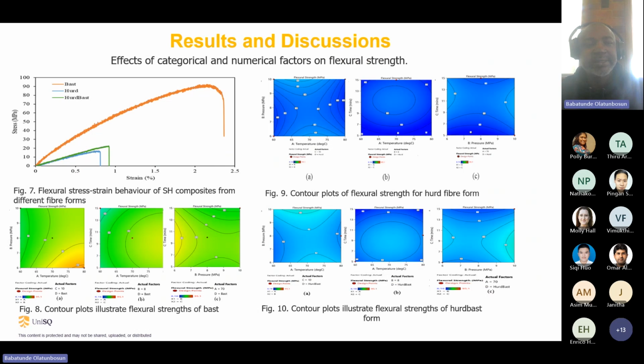The next slide talks about the effect of categorical factors and numerical factors on the flexural properties. You could see from figure 7 the strengthening behavior. How does this affect the flexural strength? The flexural strength of the hurd fiber and the bast fiber happens to be the highest, at about 91.4 megapascal. This is quite encouraging compared to other natural fibers.